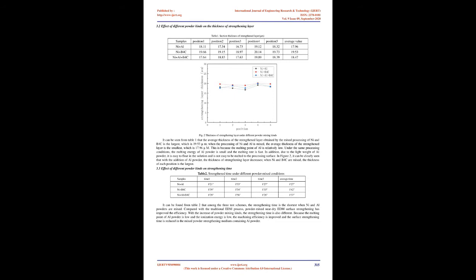The wear loss of different samples was tested by MM200 wear tester. The rotation speed was set at 200 r/min, the load was 100 N, and the test time was 7 minutes. The wear amount in the test process was recorded and analyzed. 3. Results and analysis. In Fig.